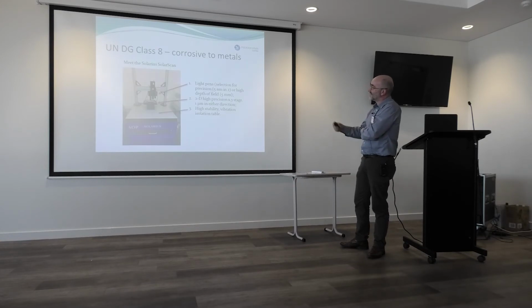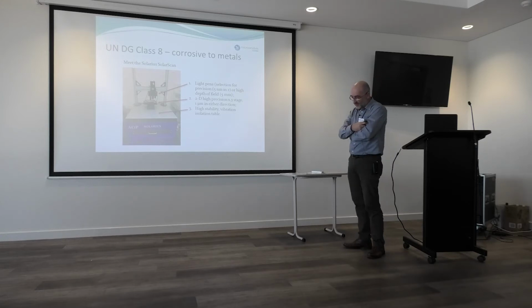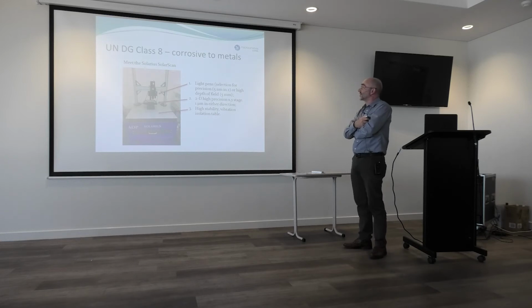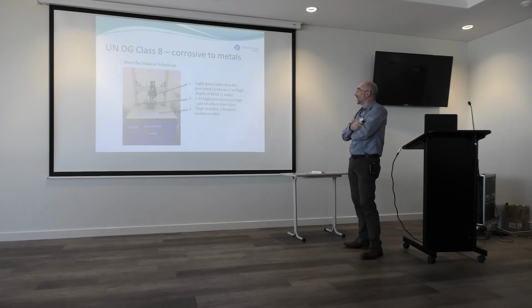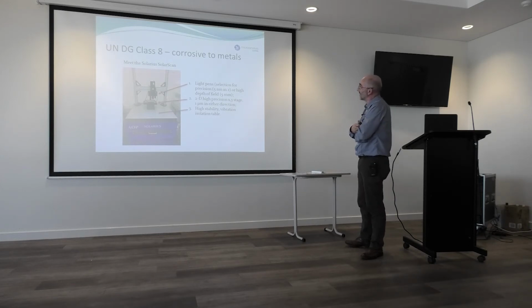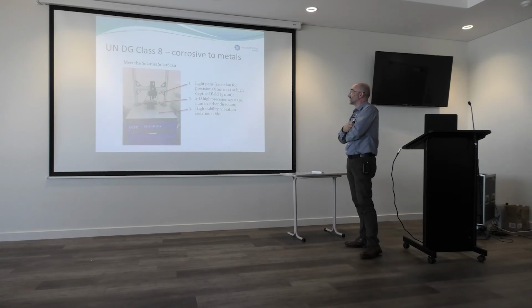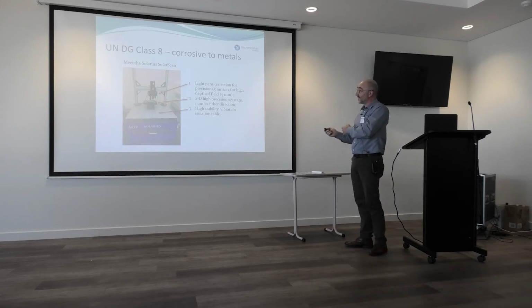So we would then take those coupons out and put them into our Solaris and do a surface profile scan. This is a very high resolution topographical laser scanner. It's got a very high precision XY stage that can be ramped down to as low as 1 micron in XY. We've got a choice of light pens, laser pens, that can give us as low as 5 nanometers in the Z direction, or we can go to a different light pen and do curved surfaces where there's a much better depth of field. So it depends on the size of the sample.